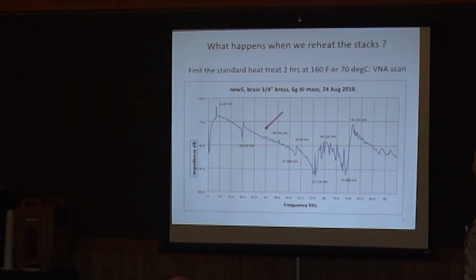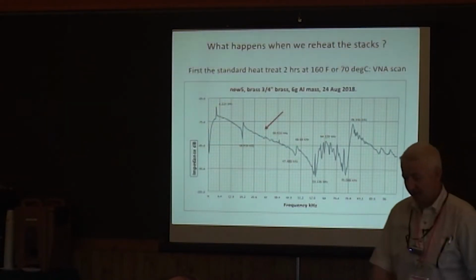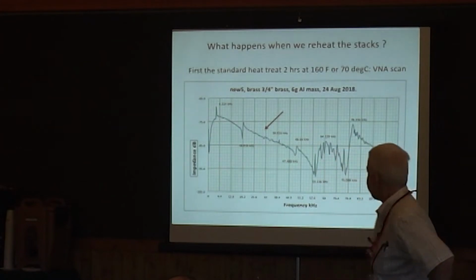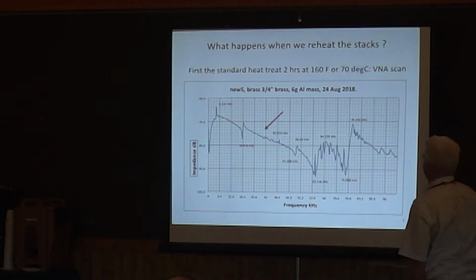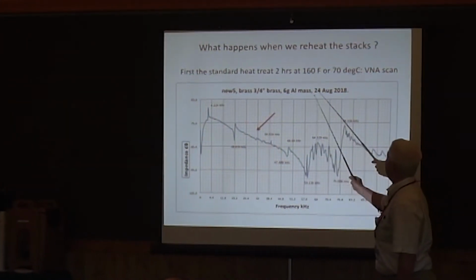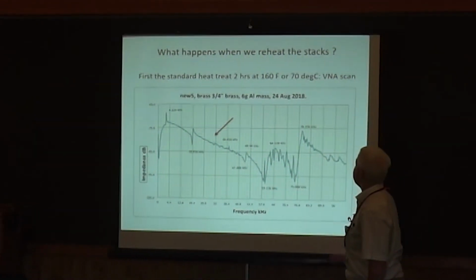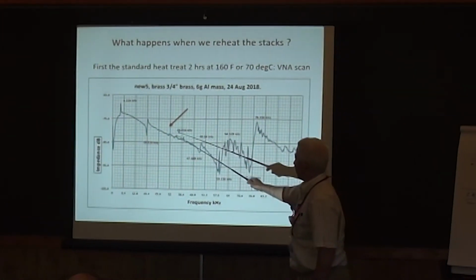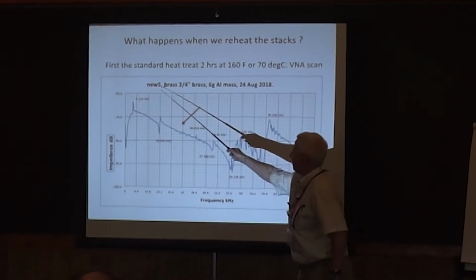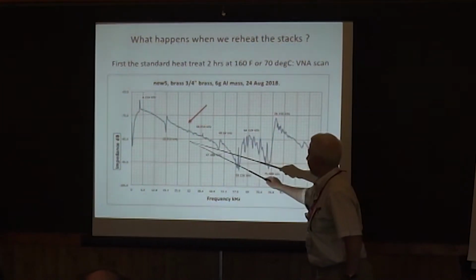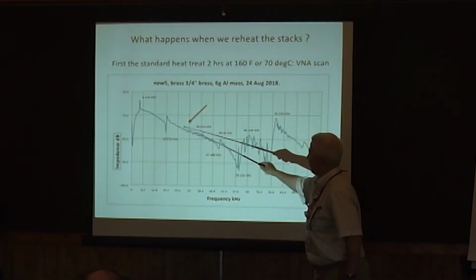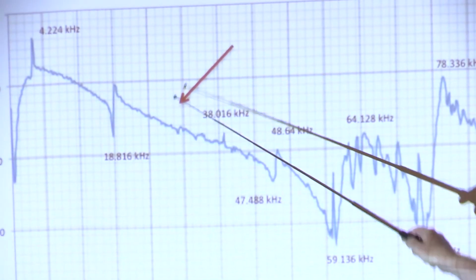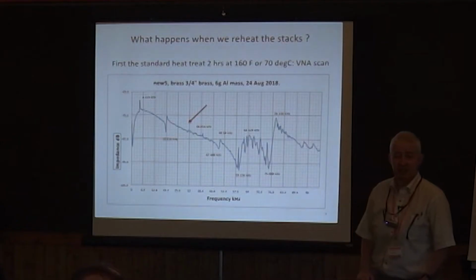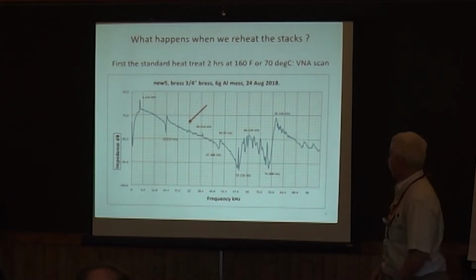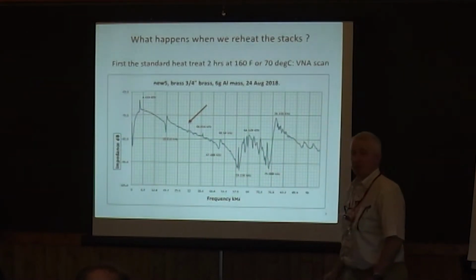So what we're going to do now, I'll tell you what I'm going to do in a minute, but this is one of the vector network analysis scans that we did when we did the 2 hours at 160F. And you notice that in this particular stack called Nu5, there's really nothing going on here. This is normally where we see a bit of a resonance dip, and that would give us the resonance at 38 kilohertz. But there was nothing here, so this one really didn't show much of anything.